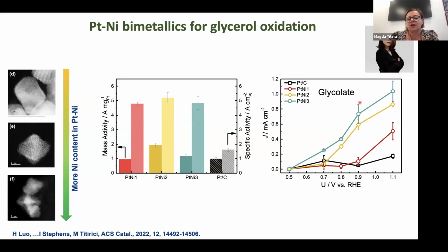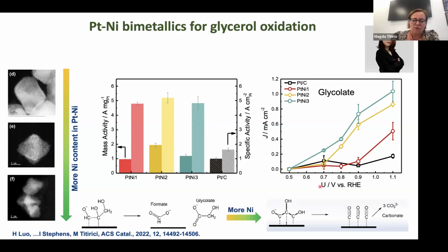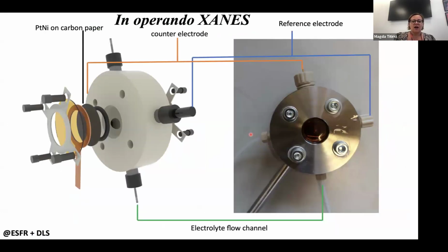selectivity toward this product, glycolate, you would see that basically the more nickel you have in the system, the more you're likely to adsorb this glycerol on the surface of your catalyst via all three carbons, and therefore you generate carbonates. And you also see that if you have one platinum to one nickel, it seems that this is the catalyst that delivers the best mass activity as well as the best specific activity.